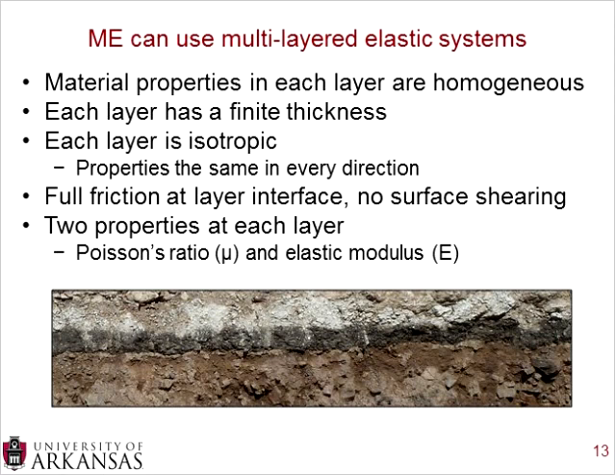Now when you're using multi-layered elastic systems, you do assume that material properties in each layer are homogeneous. Obviously, Portland cement concrete and asphalt concrete are heterogeneous materials, but you're assuming in the multi-layered elastic system that they are homogeneous. You're also assuming that each layer has a finite thickness, and this makes sense for the upper layers. Obviously you have 12, 15, 18 inches of Portland cement concrete, sometimes more, sometimes less. But when you start going down, especially into the subgrade, the natural base, you also assume that it has a finite thickness, when in actuality, the subbase is essentially infinitely deep when you're thinking about the material property reactions of it. You're also assuming that each layer is isotropic.